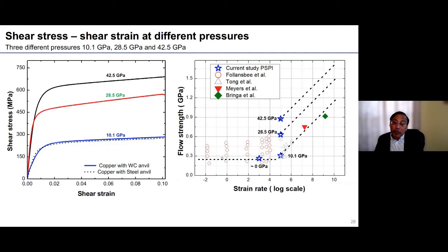These are the Hopkinson-Bar experiments, these open circles which are shown here, and these are some of the plate impact experiments from Clifton's group, and some laser shock experiments which are shown here. So as we increase the pressure, at a fixed strain rate, we see this considerable increase in the flow strength. This is again plotted on the log scale.